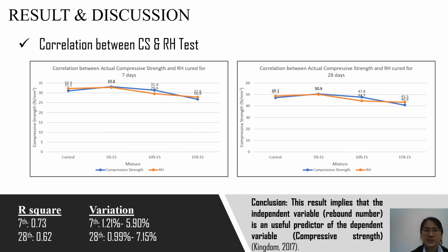The last part we are going to discuss in this research is the correlation between compressive strength and rebound hammer test. From the analysis, we can know the variations lie between 0.99% to 7.15% for both 7 days and 28 days. Also, we obtain the R-square value lying between 0.62 to 0.73, which indicates a strong correlation between compressive strength and rebound hammer test. According to Kingdom 2017, this result shows the independent variable, which is rebound number, is a useful predictor of the dependent variable, which is compressive strength.